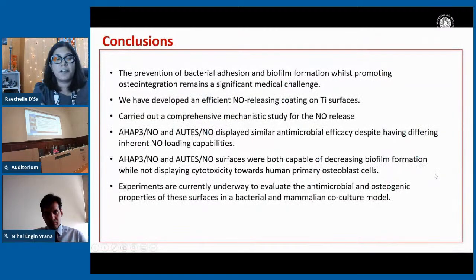So what we've been able to develop in this regard is surfaces that are capable of having an antimicrobial as well as osteoblast function. The prevention of bacterial adhesion and biofilm formation on surfaces while maintaining osseointegration is a significant medical challenge. We have just started a little bit into this direction, and we've developed surfaces that are perhaps capable of achieving both of these functions. We've carried out extensive, comprehensive mechanistic analysis for the nitric oxide release, and we have found 2 surfaces that are capable of having that dual function.